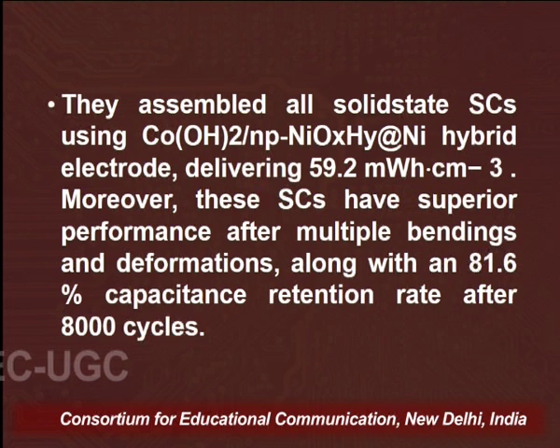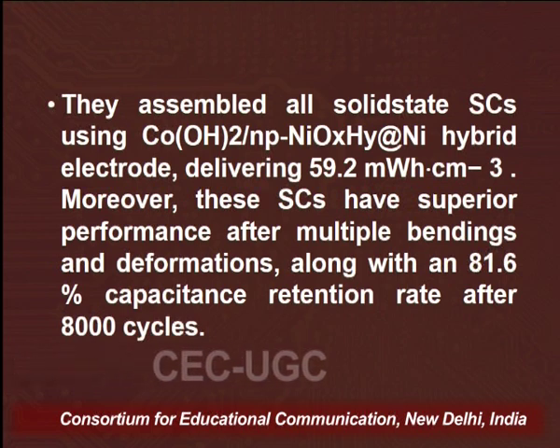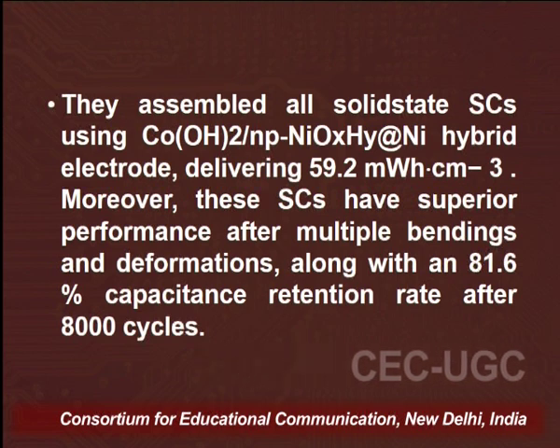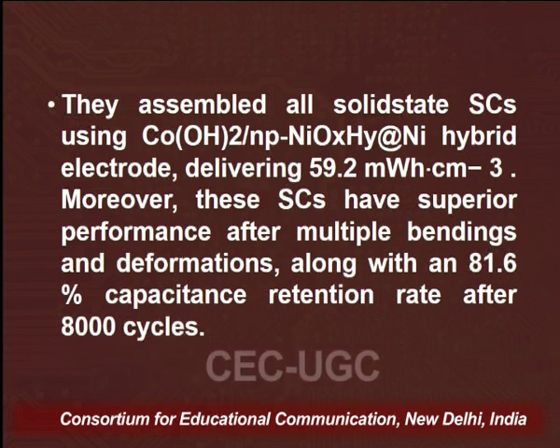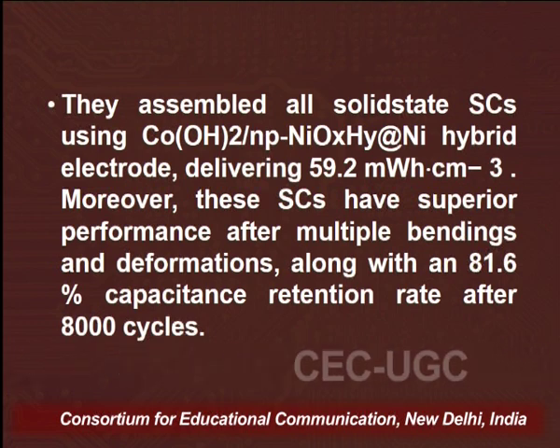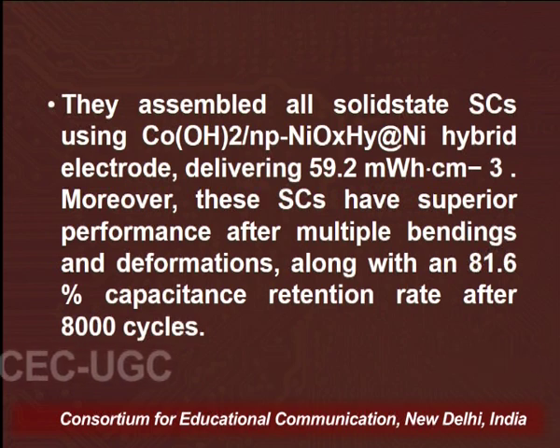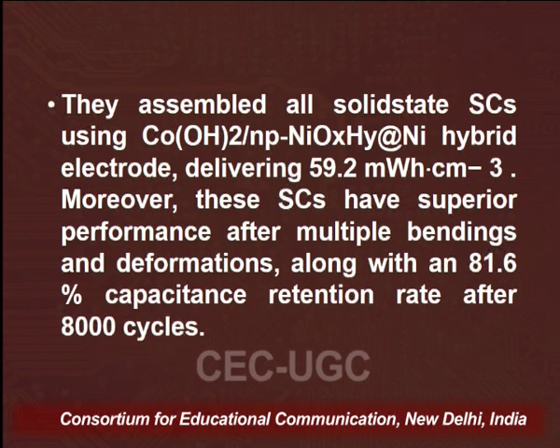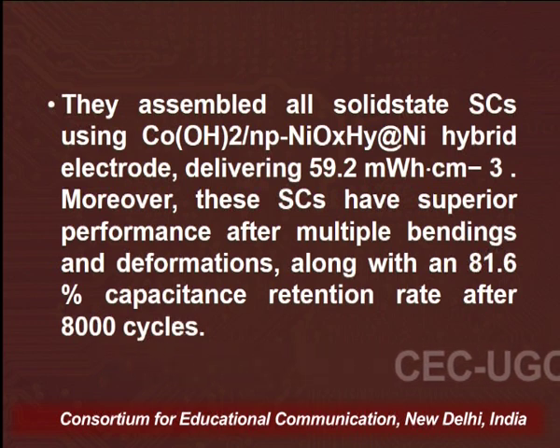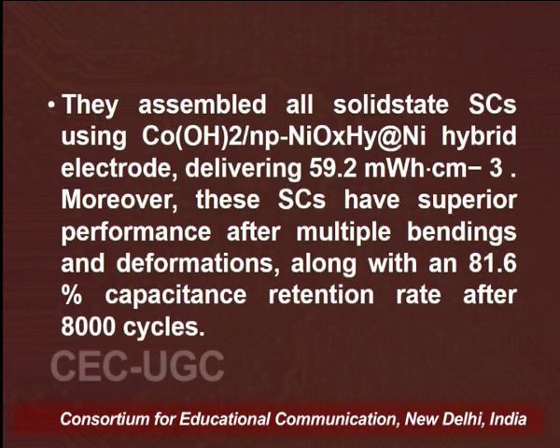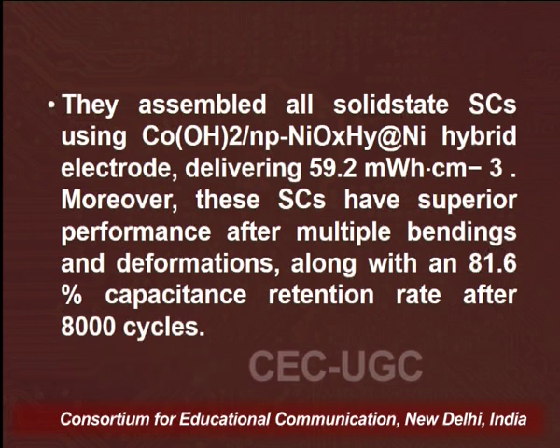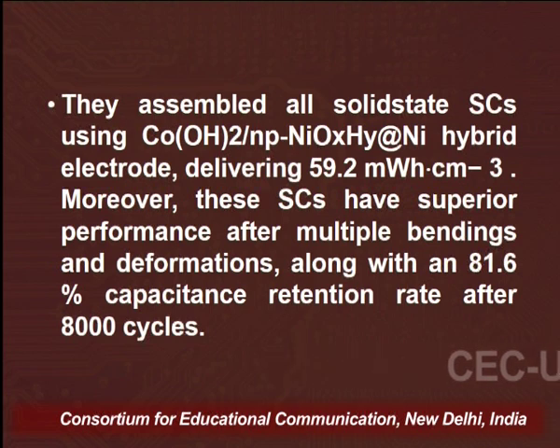They assembled an all solid state device using the hybrid electrodes on nickel foil, delivering 59.2. Moreover, these supercapacitors have superior performance after multiple bending and deformation, along with an 81.6% capacitance retention rate after 8000 cycles. It also has a long cycle life.